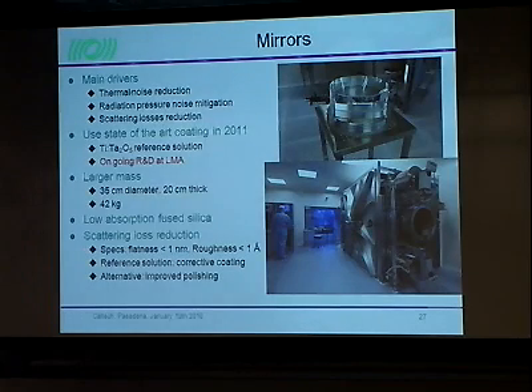So let me move now into the mirrors. The main drivers there are the reduction of the thermal noise, the mitigation of the radiation pressure noise, and the reduction of the scattering coming from the mirrors. The solution is to use the state-of-the-art of the coating as it will be in 2011, when we will have to actually put the coating on these mirrors. Very likely it will be titania-doped tantala. We will have to use larger mass to reduce the radiation pressure effect. So this will be 42 kilogram mirrors made with fused silica, 35 centimeter in diameter and 20 centimeter thick.